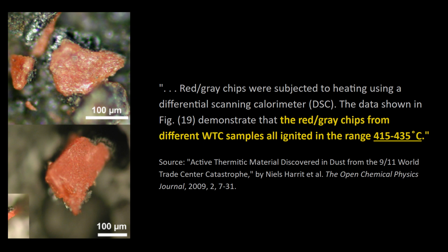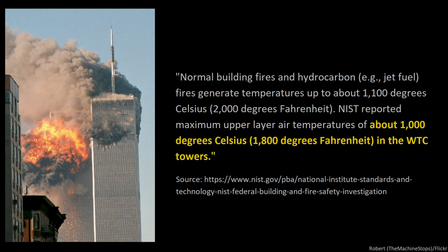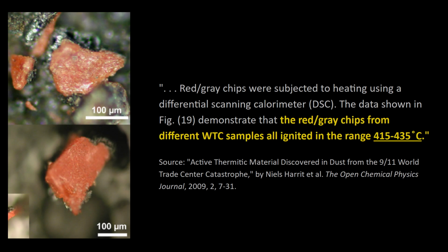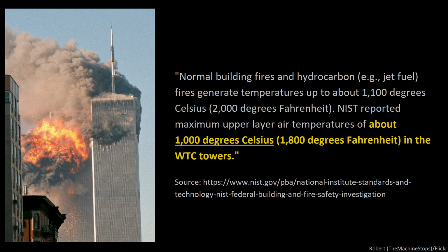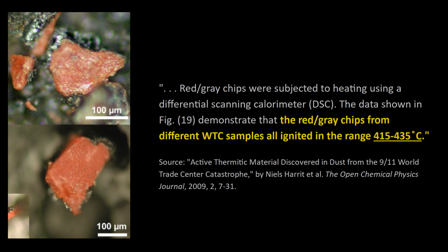I would also note that building fires get much hotter than 415 C. NIST reports that, quote, "normal building fires and hydrocarbon, for example jet fuel fires, generate temperatures up to about 1100 degrees Celsius. NIST reported maximum upper layer air temperatures of about 1000 degrees Celsius in the World Trade Center towers," end quote. So if these red-gray chips are ignited at about 430 C, why would the building fires alone not immediately trigger a cascading thermitic reaction? Nothing that they're arguing here makes any sense.